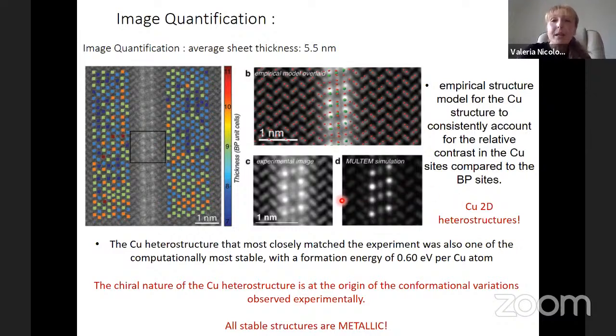So it was interesting because the very first thing that one might have thought was that these were wires growing on the surface, for example, and just instigated by a temperature gradient. This was not the case. Indeed, we were building copper walls into our black phosphorus structure. And we understood that by doing this, we were creating structures that were fully metallic, and we could do some nice engineering there. So we are now in the process of trying to build devices with this, which is a very interesting and complicated matter.